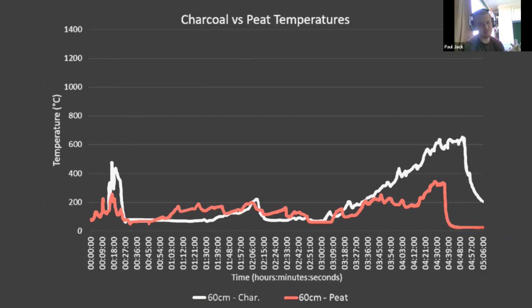There's this big thermal performance difference that isn't really apparent until the last hour or so, where the wood charcoal has sort of a bit of a second wind, which the peat charcoal maybe starts to have, but it's not the same. And I suspect that the reason for this isn't an inability of the peat fuel, but actually a result of blockages within the furnace.